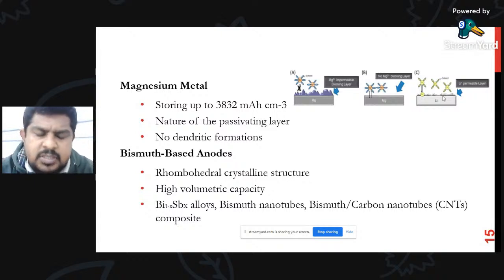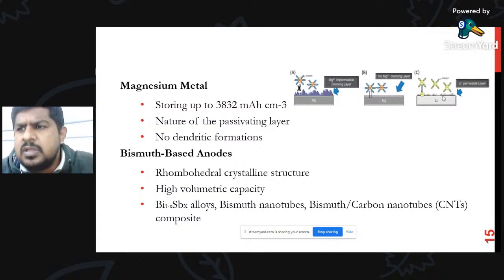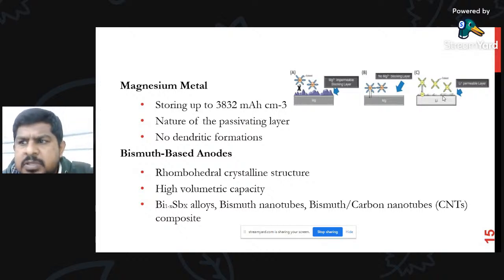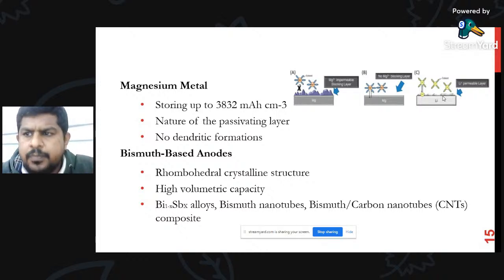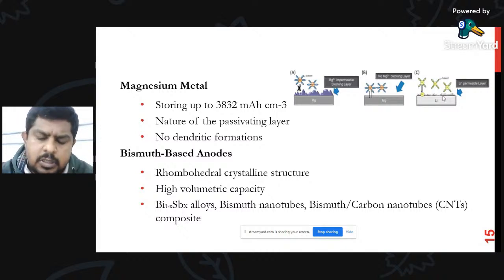There are also losses actually, because when the researchers tested bismuth anodes, the capacity faded. This is because the electrolyte is in contact with the bismuth anodes, so there is a periodic volume change over a long time of use. So this bismuth anode also gets faded after a long time.